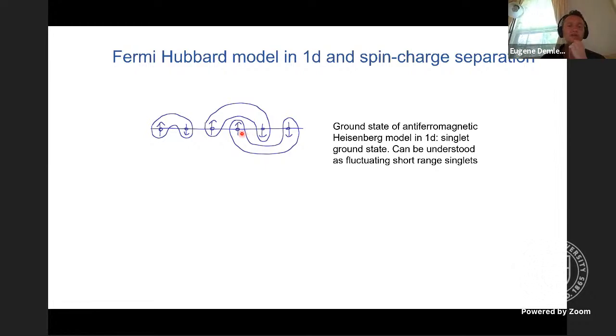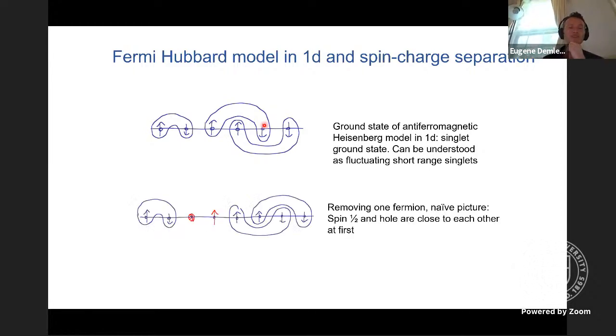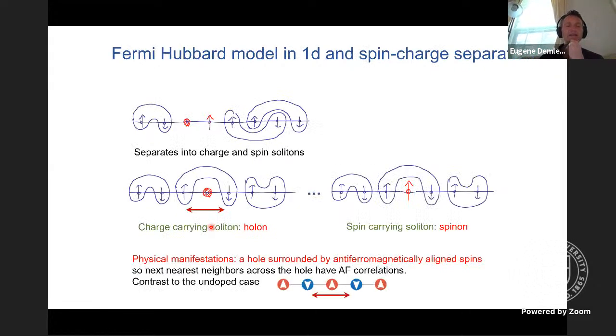have broken symmetry. So as a result, the state should be really thought of as a combination of short-range singlets. So all the spin 1/2 fermions are bound into singlet pairs, which are fairly small. Now imagine that we remove one of the fermions, like here we have an empty site. But what this also does is it creates an unbound spin 1/2, right? Because it used to be part of, let's say, a spin singlet configuration, but now the partner has been removed. And what happens is that if we let this configuration relax, so even if we let it reach the ground state, this object, which is an empty site, and an object which is just an unpaired spin 1/2, they separate, and now they can propagate separately.